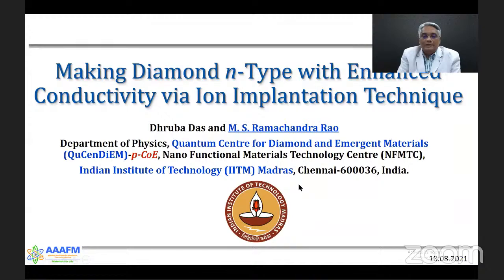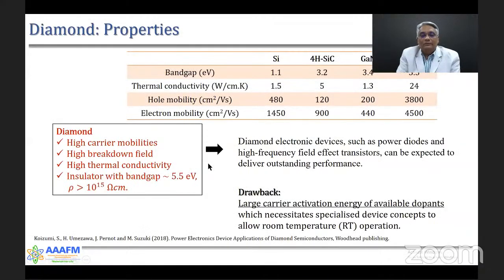As you know, diamond is a very fascinating material with a plethora of very interesting properties. It has a very large band gap of 5.5 electron volts. It's an insulator, but it can tune its conductivity by doping. Boron doping makes it a p-type semiconducting system, and with higher concentrations of boron doping, you can even realize superconductivity.